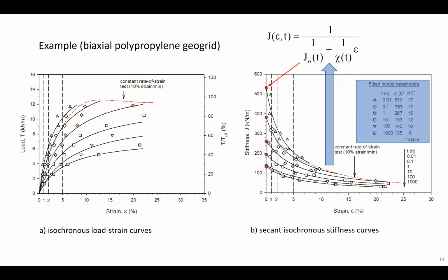So what you see on the left-hand side are a series of load strain curves for a polypropylene geogrid. And using the procedure that I mentioned to you before, we constructed the secant isochronous stiffness curves for this data. And you can see that for each isochronous curve, there's an intercept, which is the J naught term, and the chi term is a measure of the curvature of these stiffness curves.